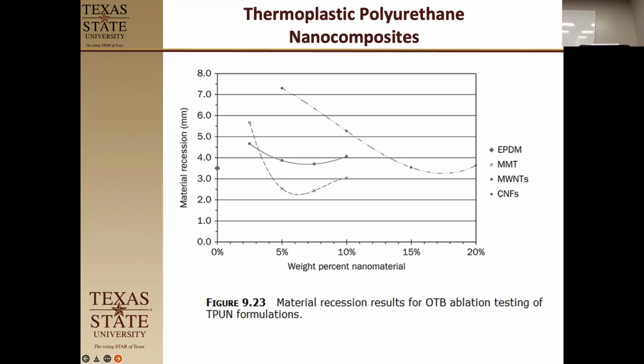You have less of that charred polymer to act as a binder, carbon composite binder. And so at some point, it's just going to be all powder and it can't stick together for a while. So you're going to see that happen a lot. And then with this right here, you see that same dip in the multi-walled carbon nanotubes. And again, both of those seem to have higher losses, probably due to the thermal flux. But the montmorillonite here performed quite well compared to that. And it even performed better than the EPDM. So this is actually finally a good positive response.